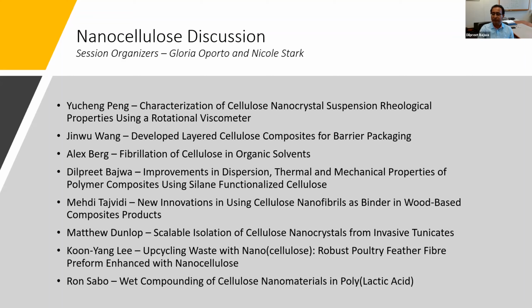We created these films with different amounts of silane, and we tried to characterize the CNC modification, whether the amine was attached to the cellulose nanocrystals, and we looked under the TEM whether there was improvement in dispersion, because that was one of the main goals of this research. Obviously we also looked at whether mechanical properties improved using DMA, DSC, and crystallinity, as well as thermal analysis to see if there is any improvement in the thermal stability of these composites made from PEO and functionalized CNCs.